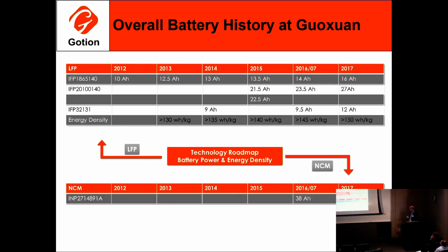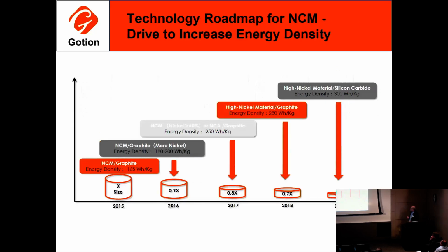So where does this go from a futuristic perspective? This is kind of an indication of where it is now. A couple years ago we were at 165 watt hours per kilogram, and by 2019, 2020, we'll be using the high nickel materials and the silicon anode mixture with graphite, and we'll be at the short-term holy grail target of 300 watt hours per kilogram. So the capacities are going up, the energy density is going up, and the size is going down. That's pretty much what the market needs, and that's where we're headed.